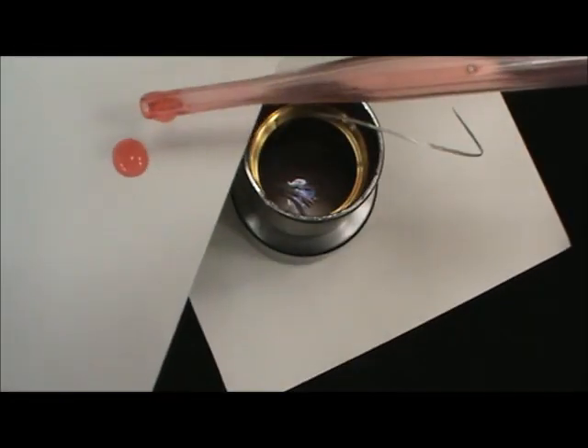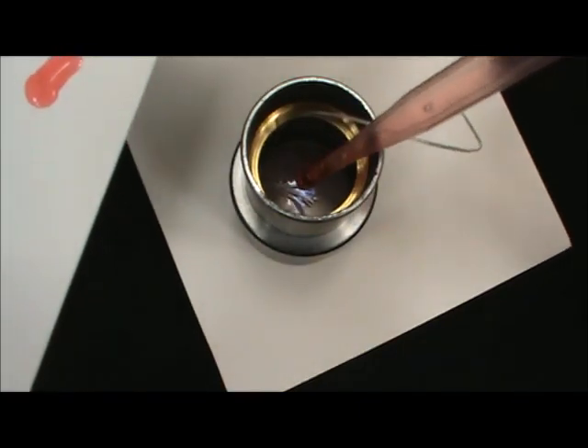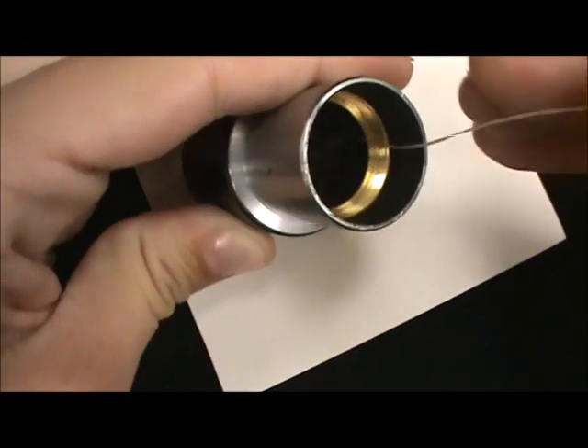Allow it to dry until there is no solvent smell. Then, carefully pull the exposed end of floss. Once the polymer starts to lift, it will easily peel out of the cavity. If you need to spot clean some dust or water spots, floss will lift polymer that is not on an edge.